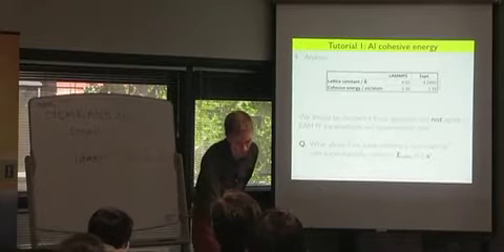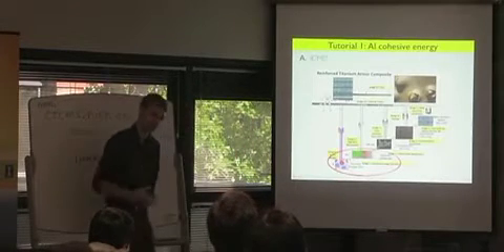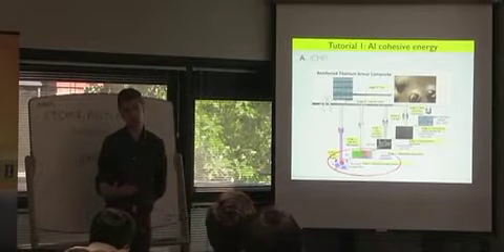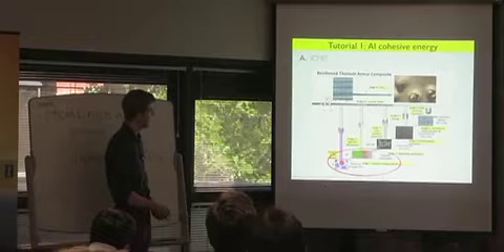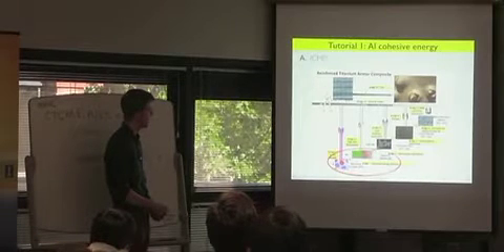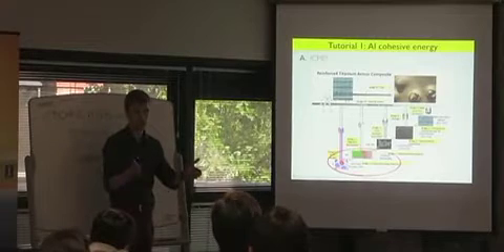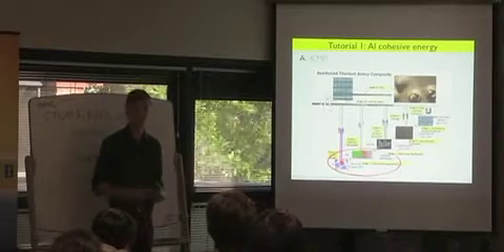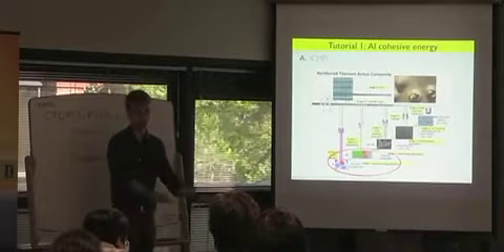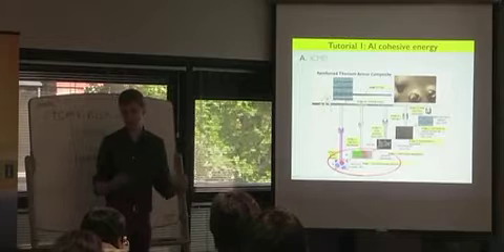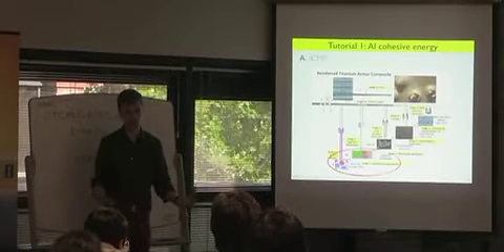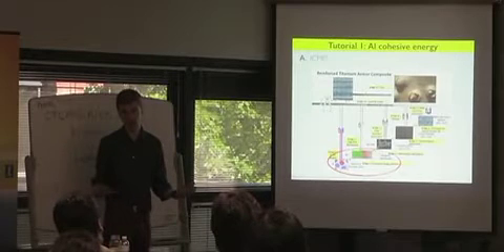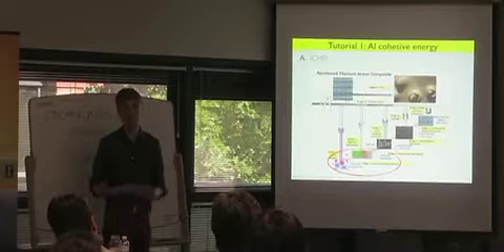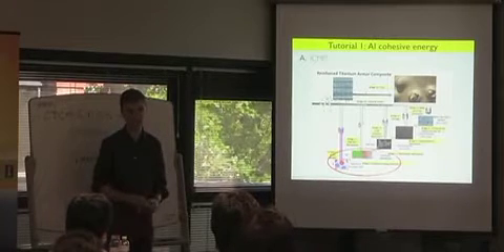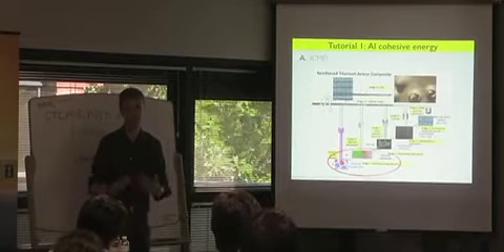Okay, and so that's sort of the question there. If we're studying a new material with experimentally unknown cohesive energy and lattice spacing, this is where I'm trying to make a bridge to integrated computational materials engineering. Perhaps what we could do is some electronic structure calculations down at this very low level here and bridge the cohesive energy and the lattice spacing we calculate from, for example, DFT, to help parameterize a new EAM potential we could then use in molecular simulation. So why would we want to do that? If we can calculate things at the electronic level, why should we worry about making a classical potential? Well, perhaps you want to go to longer time and length scales. So you want to simulate things for, you know, microseconds over nanometers. DFT is not going to get you there, but perhaps DFT can give you a good classical approximation for a force field that can get you there.